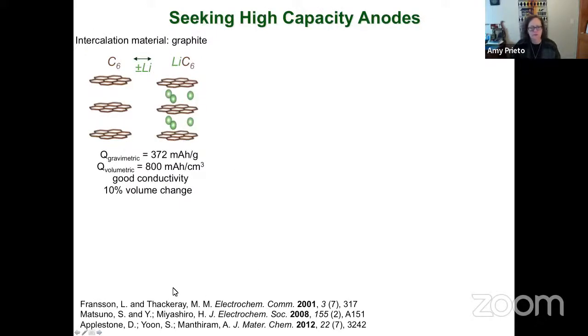Okay, so why copper antimonide, which is maybe an unusual choice? What we were looking for were anodes, again, that were really good metals. So we were looking for high capacity, but that in and of itself is not sufficient. It really has to be something that is metallic so that it can conduct electricity well without the need for binders. So here I'm showing you graphite, which is really the canonical anode material. 1 lithium atom per every 6 carbon atoms. And I'm showing you the capacities in gravimetric and volumetric terms. I'm showing you the pros, which in this case is good conductivity and a pretty small volume change upon lithiation.